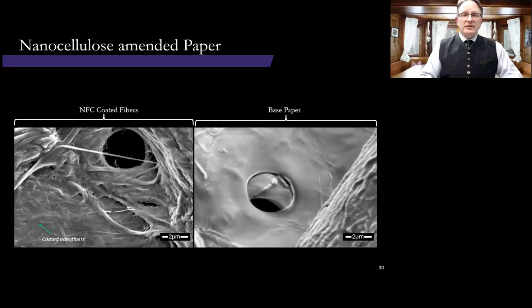If we increase the magnification and look at the surface of the sheets, this image shows two fibers actually. This is a pit in the outer wall of one fiber. And you can see going across the surface these small little shadows of nanofibrillated cellulose. And if you look at the boundary between the overlapping fibers, it's not very discrete, and you can see quite a bit of bridging in it. If you look at the same magnification with the base paper, I tried to find one with a pit as well, you can see that there's a very clear delineation between fibers. And so this demonstrates that our retention system managed to capture the NFC fibers sufficiently.